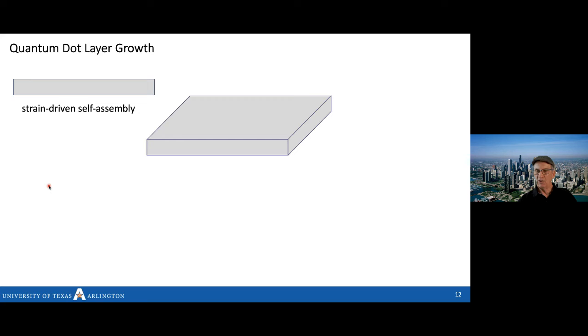Strain semiconductors. We were able to find that if you take two semiconductors with different lattices, if the layer of the larger lattice, for example, is larger, the fact that they're grown together will cause it to strain. And if it strains too much, it becomes useless. But if you strain it a little bit, it turns out it changes the physics in a way that can turn out to be reliable, even though your expectation is any strained system is eventually going to fail.